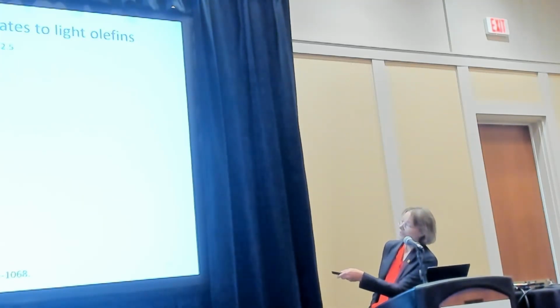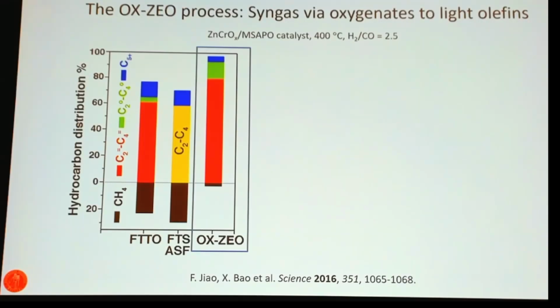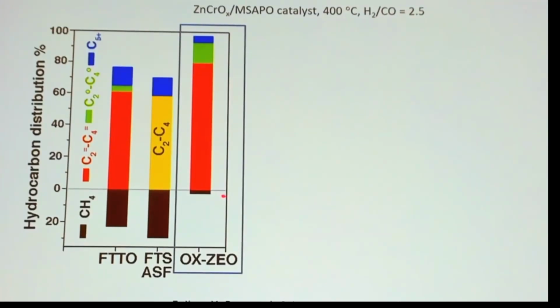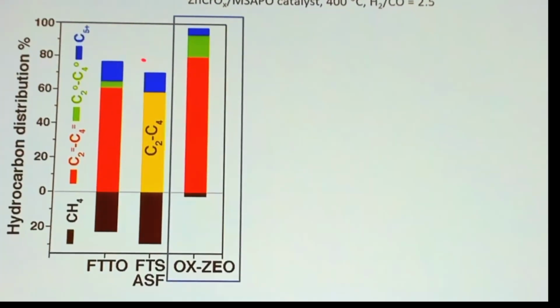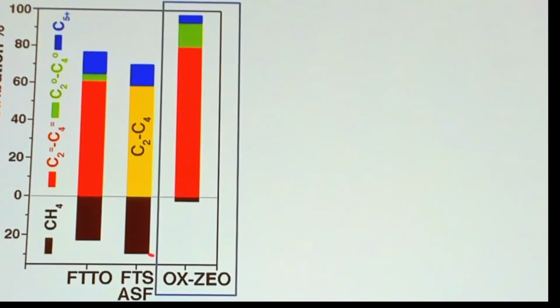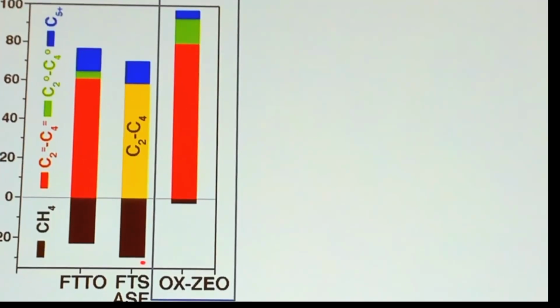So the scientific community learned about this process mainly when, as we saw from the previous talk also, the Bao group and one group from the Dalian Institute published these tandem systems: zinc chromium oxide and zeolite catalyst, 400 degrees and syngas feed. And they could demonstrate a very high C2-C4 olefin selectivity, some hydrogenated C2-C4 and some heavier products, and very little methane compared to the Anderson-Schulz-Flory distribution of the Fischer-Tropsch process that you see here beside.